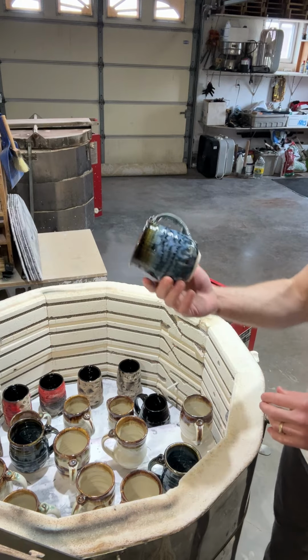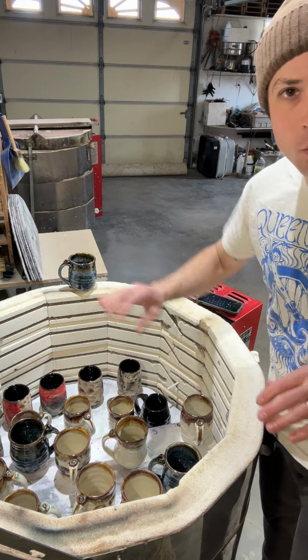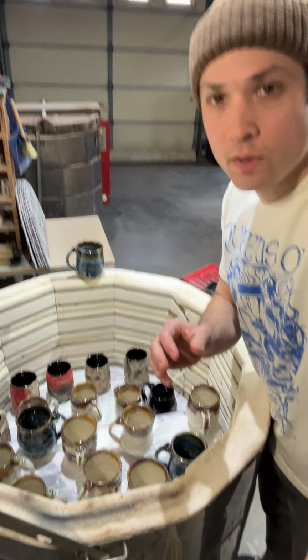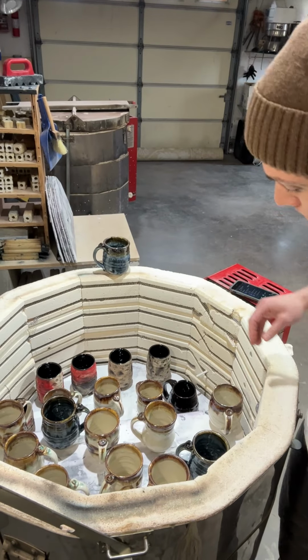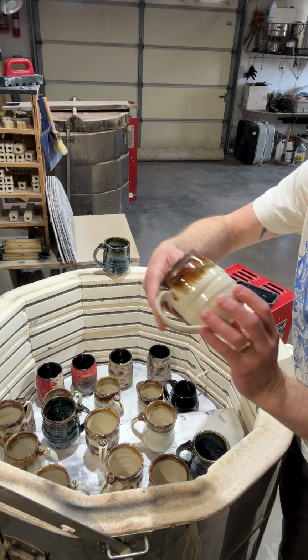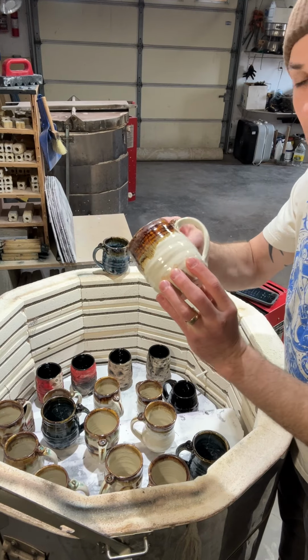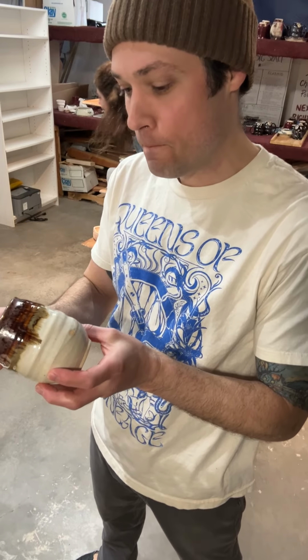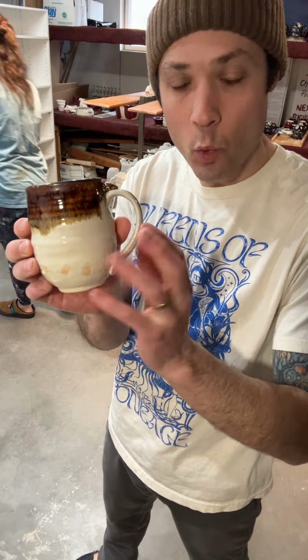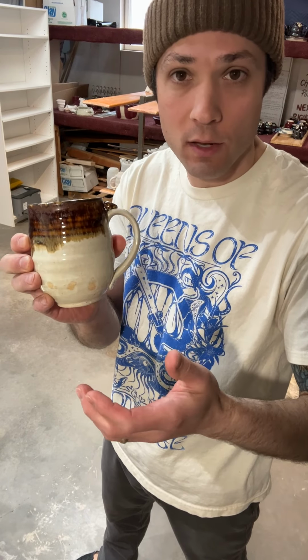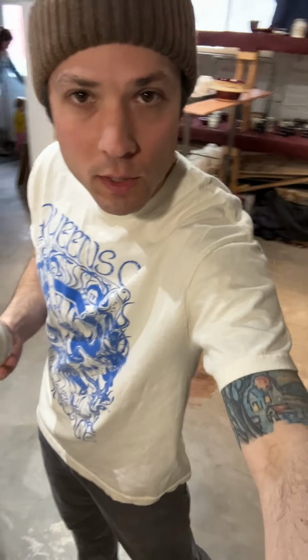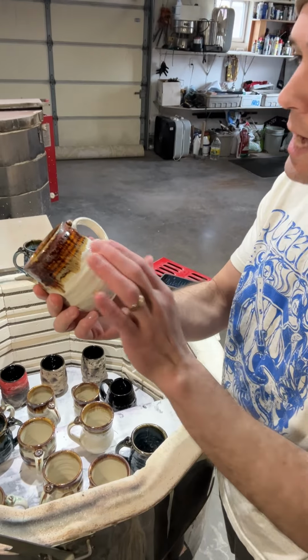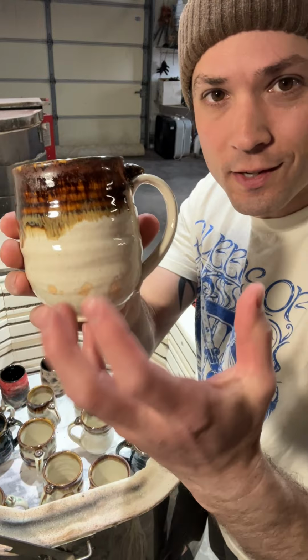All right, so this was a cone 9 firing, which is about 2,300 degrees Fahrenheit. And most of them are in this Nuka glaze. I call it Nuka, which means it's a Japanese word. I don't exactly know what it means, but it has ashes in the glaze. So about 20% of this glaze is wood ash that I get from friends who heat their homes or shops with wood burning stoves, which is really common here in Minnesota. And the ash is what gives this rustic qualities.